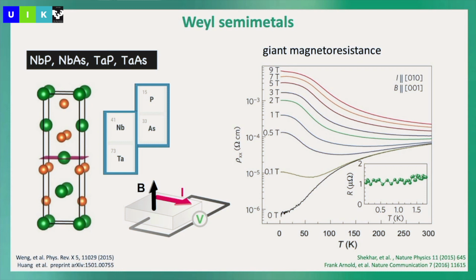And for us, it was really amazing, like all these materials we are now making, suddenly people predict material. So I think there was a time when people were talking about large magnetoresistance effect for spintronics, like Stuart Parkin became very famous because of this, and they had effect like 100%, okay? So it's a factor of 2, okay? But you see now in these materials, you see even much more giant effect, and nobody has measured these simple compounds, you know, because everybody measures only what there was some prediction, but here even at room temperature there's still large effects.